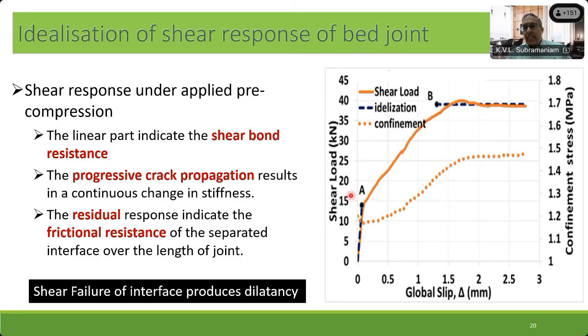So here the crack is forming, and as the crack is forming, you see that the confinement starts to increase. That's because as the slip starts to happen, the rough crack faces start to move against each other. There's dilation happening, or basically the two faces are being pushed apart as they slip past each other. And as they're being pushed apart, because we have kept this threaded rod assembly, the confinement starts to increase, because now the bolted setup suddenly starts seeing more tension. And so you see more and more confinement,